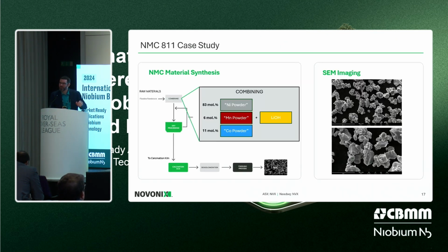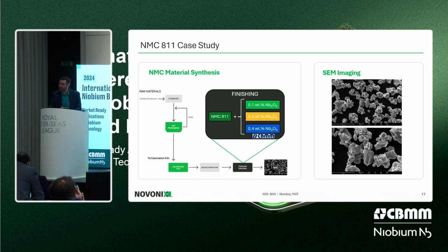So very similar to the first case study, we synthesized NMC 811 that's devoid of dopants this time, in weight percents listed on the screen, of an 811 material using nickel powder, manganese powder, and cobalt powder in an 83:6:11 ratio. Where does the niobium come into play? Well, that's down here in the finishing process. So we are really filling in the matrix of tests to understand and optimize what we can do to maximize performance by adding the right amount of niobium.